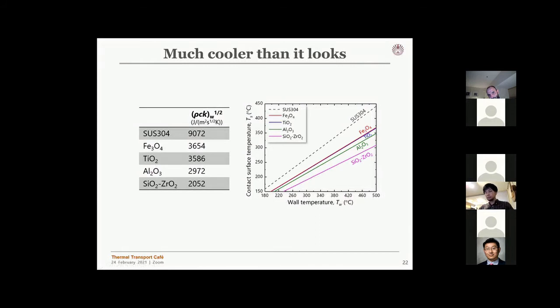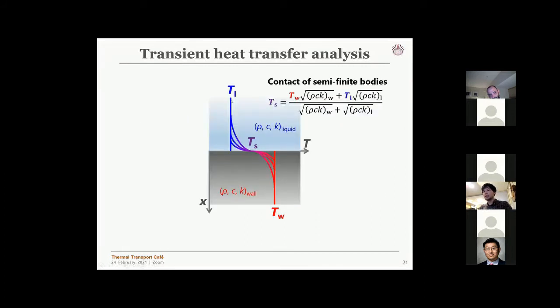This means that when these two bodies, droplet and wall, come in contact, you have a temperature drop from the wall and a temperature increase from the liquid. At the interface, where these temperature profiles meet, we have this interfacial temperature.